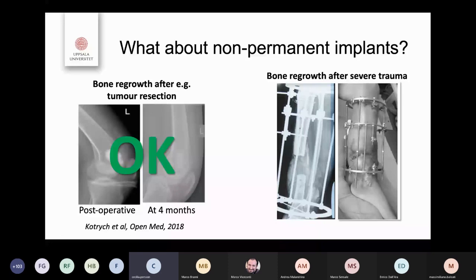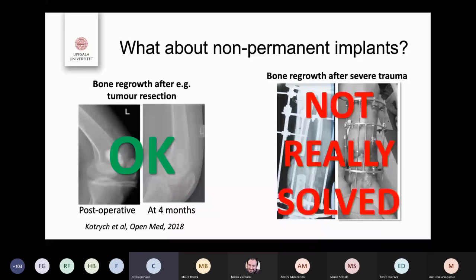So what you may have to do then in order to get bone regrowth is actually to make a new small fracture that can heal by the body itself. And then you move this piece of bone towards the other one very slowly over time, so about 0.5 millimeter per day. And this can, of course, take between 6 and 12 months, unless you get an infection, and it, of course, takes a lot longer. So even though it's fantastic that you can actually have bone regrow in this way, from a degradable material perspective, it's not really solved.